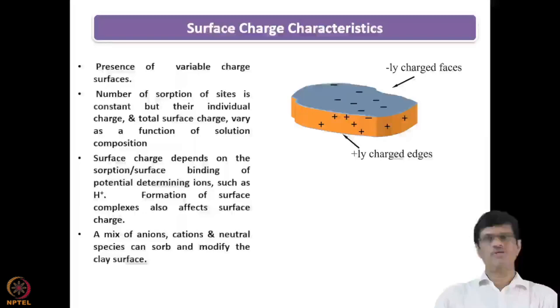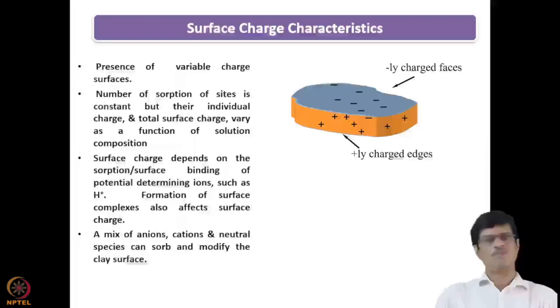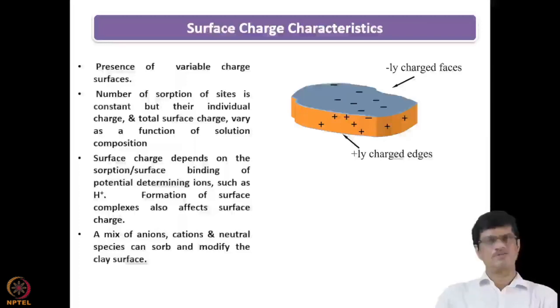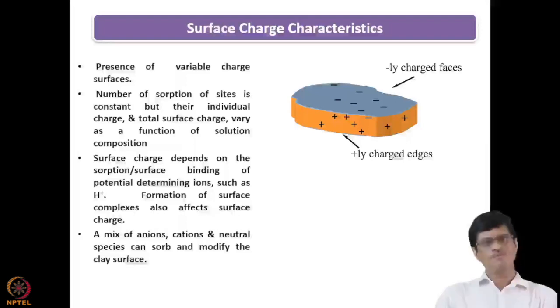So naturally the uptake of the protonated species will not occur onto this mineral surface. But if we increase the pH to higher than the PZC, then these hydrogen ions are dissociated or removed from the surface, giving O-minus or negatively charged species at the surface, which will form complexes with cationic species present in the aquatic system. If an anionic actinide species is formed, it will not form a complex at pH higher than the PZC.